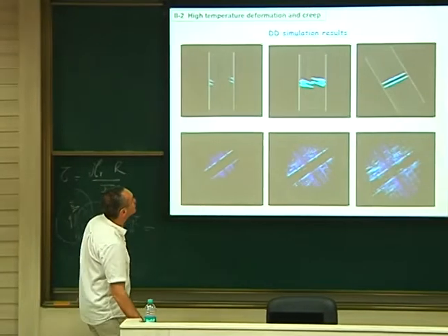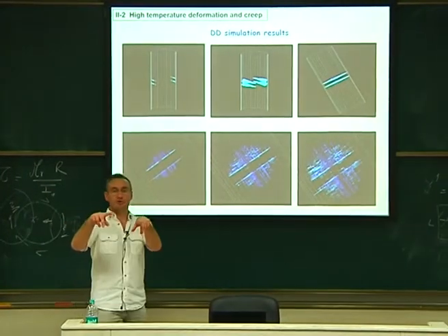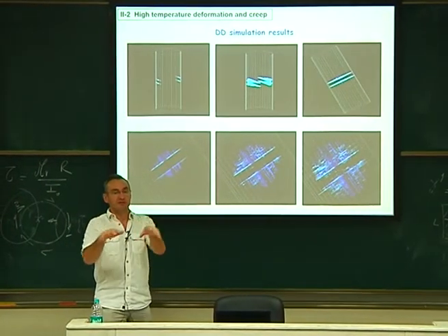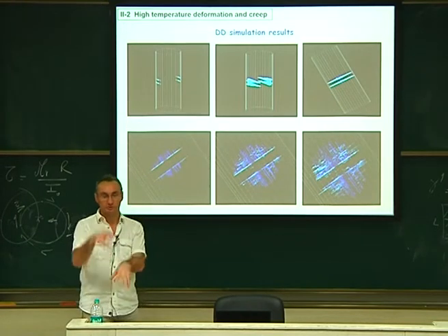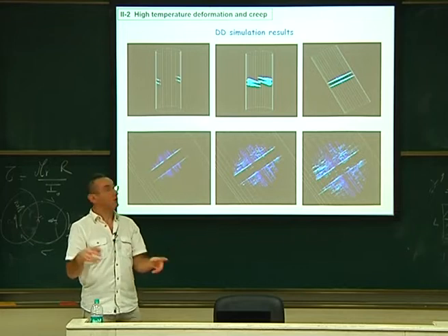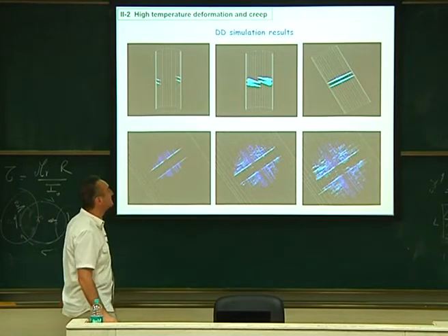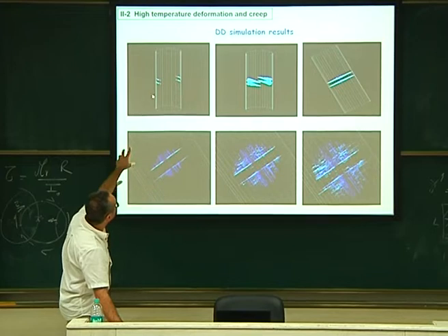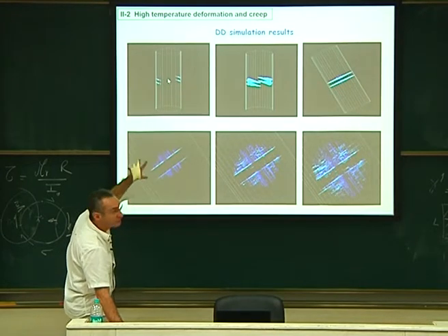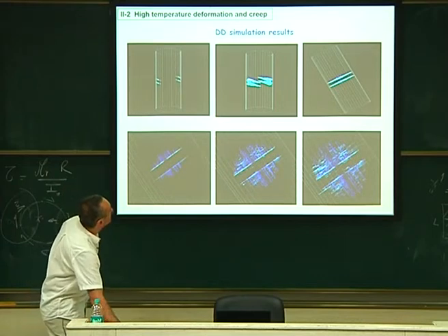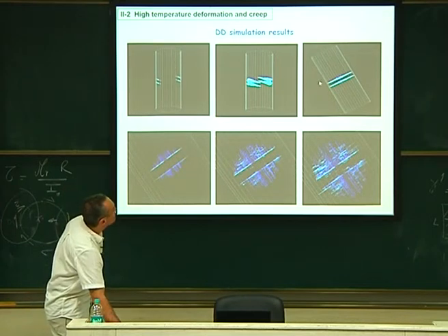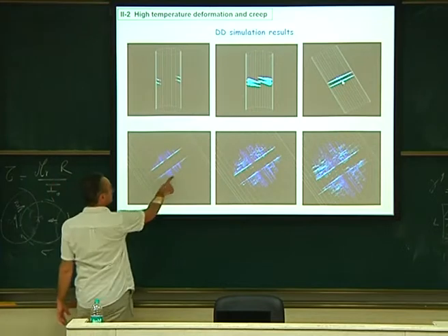Here I put two sources just to be sure that the cross-slip starts. Because if I have a single one, it will be hard because it's exactly 0 in my plane. So I should either put a noise to trigger the cross-slip, or I put two planes. So this is two planes with only two Burgers vectors. I don't put the three of them, only two, just to check if this works. You see that they propagate and reach the center, and when they reach the center, you already see some dark blue segments that you can zoom here.